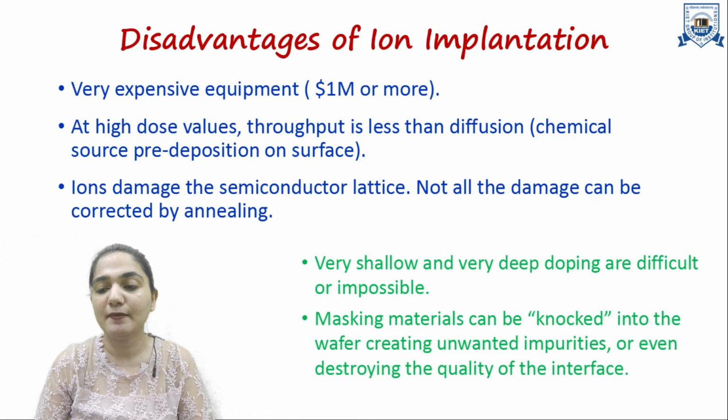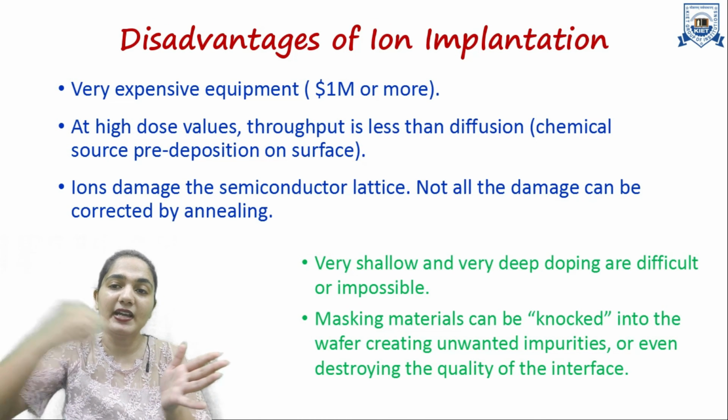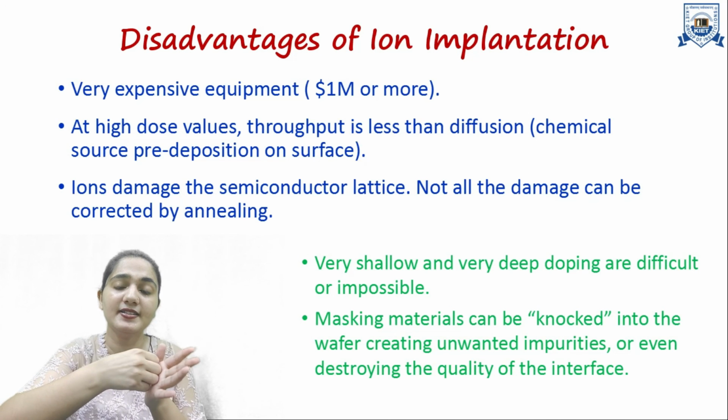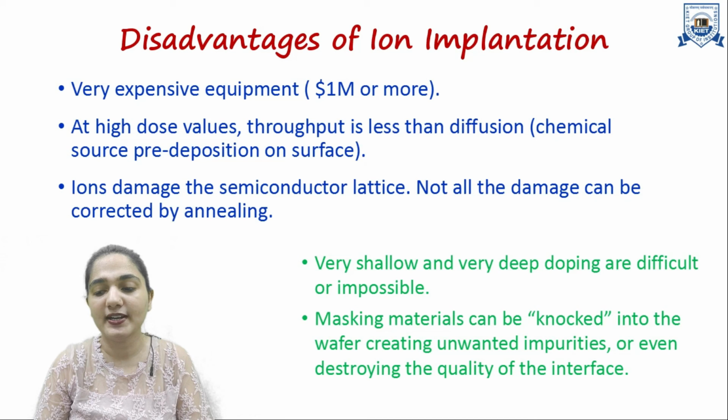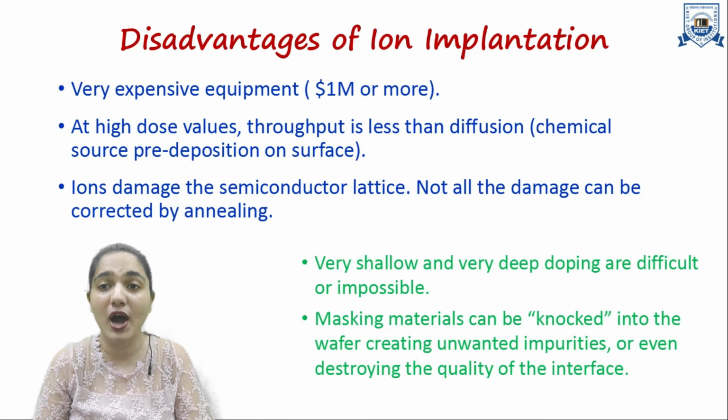Very shallow and very deep doping are difficult or impossible. Masking material can be knocked into the wafer, creating unwanted impurities. When I am hitting with high energy ions, sometimes the mask also goes inside the substrate, creating impurities which change the electronic properties, which we have to control highly. So it will degrade the quality of the interface.